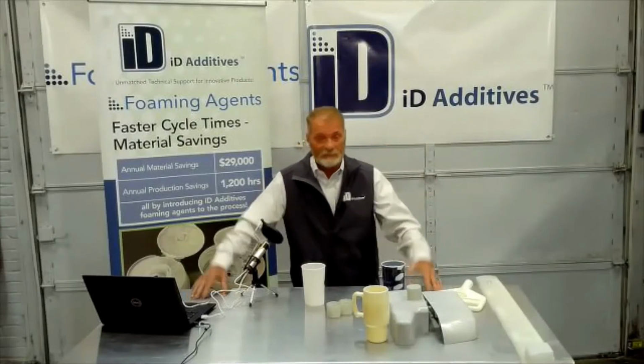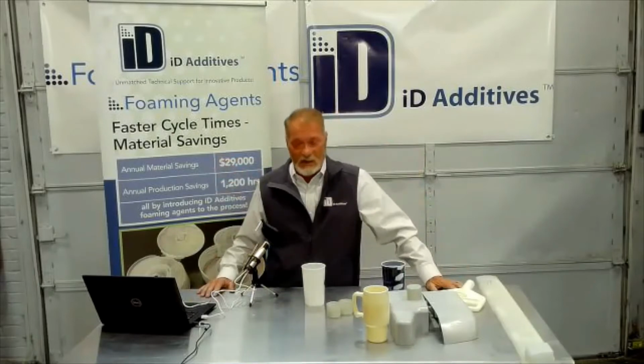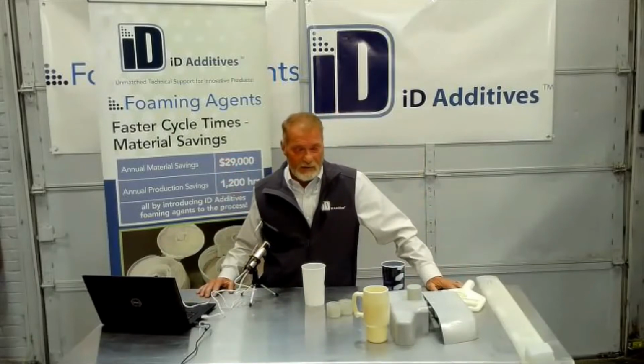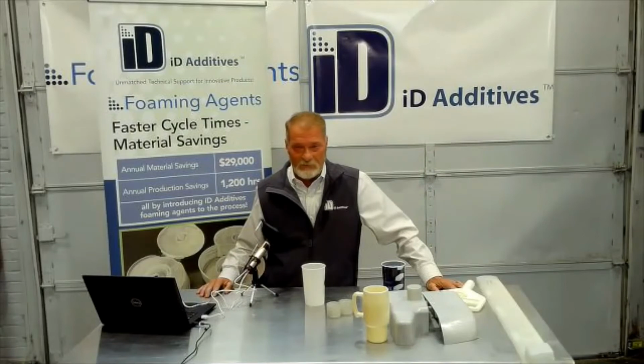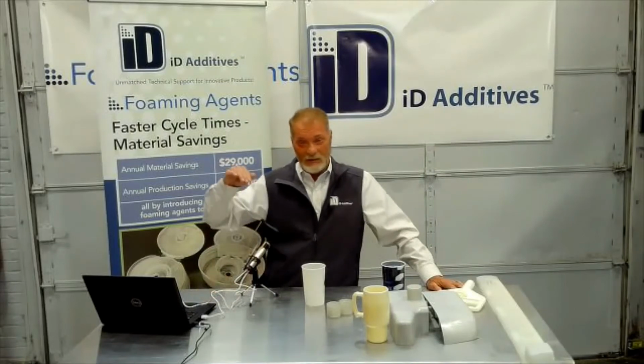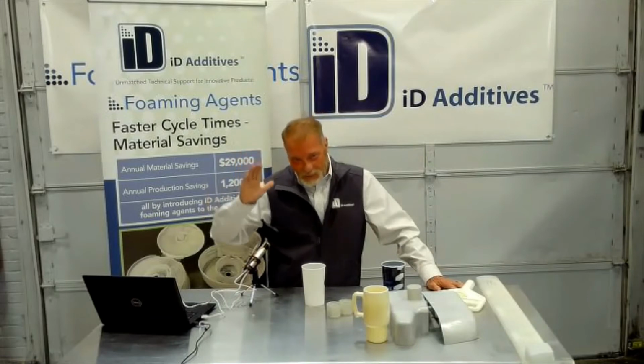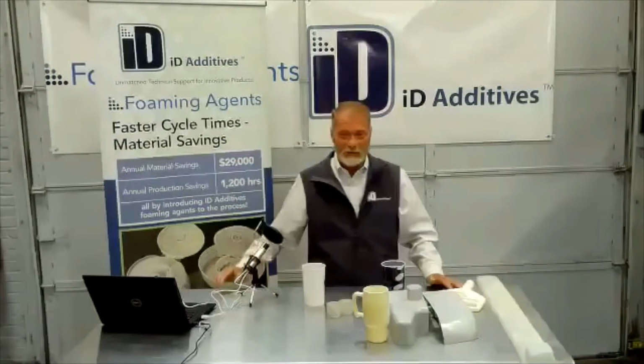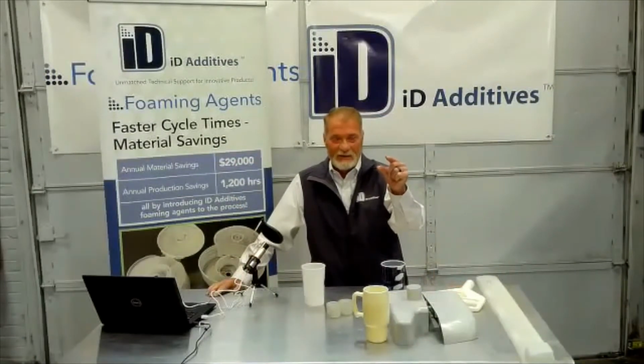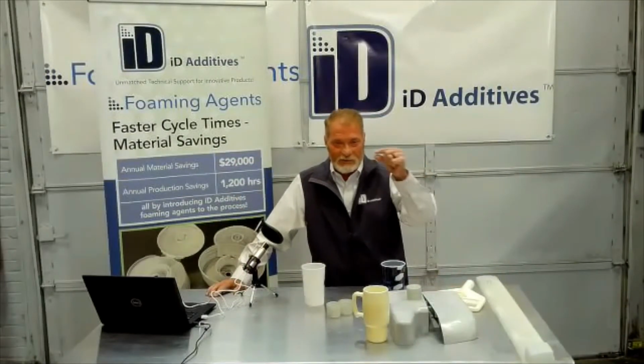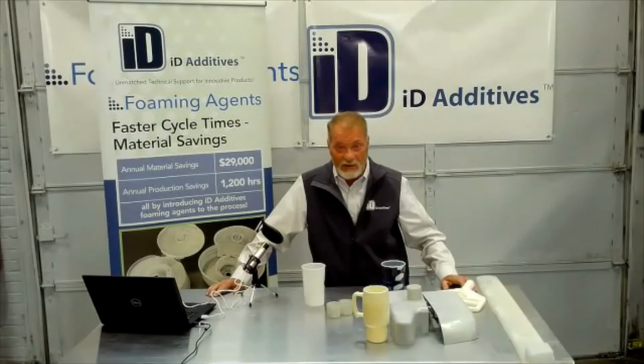You're not packing it. It fills the part, and I've had parts where they had flash, and we added foam and virtually got rid of it. That metal was hobbed over, and with the hob you're going to get a little bit there, but they were flashing that far out, and we took that down to virtually nothing. So absolutely.